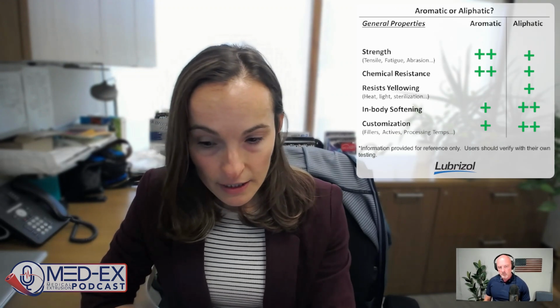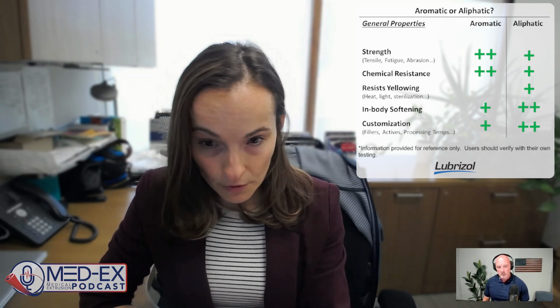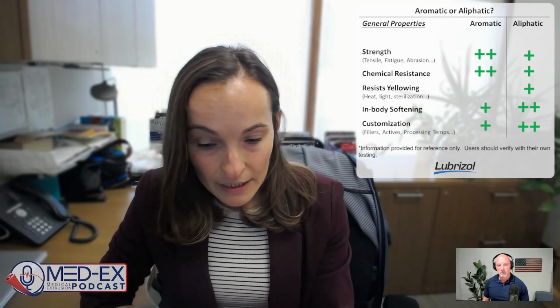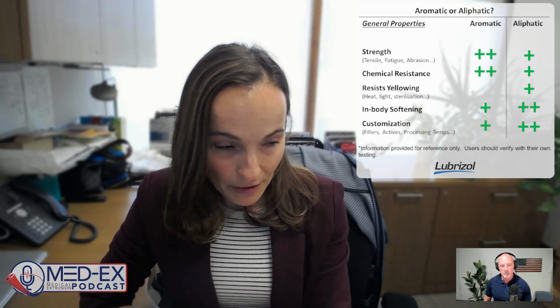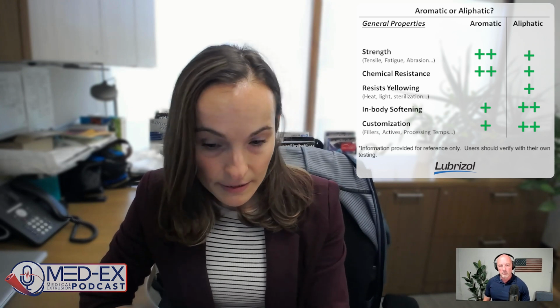Sure. So traditionally, polyurethanes used in medical devices can have either an aromatic or an aliphatic isocyanate in the backbone. The aromatic isocyanate tends to give the material superior strength and chemical resistance. It basically stacks up better in terms of how the polymer chains behave. It allows better and tighter packing. So that's what gives it the strength and chemical resistance.